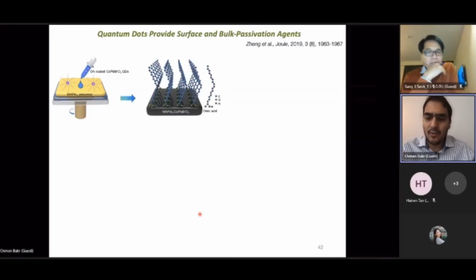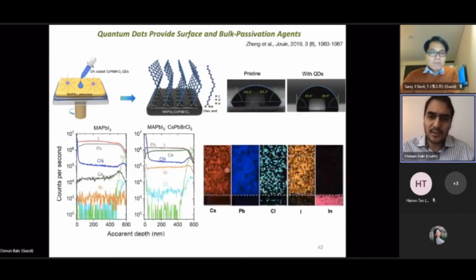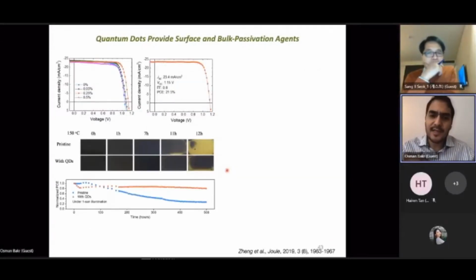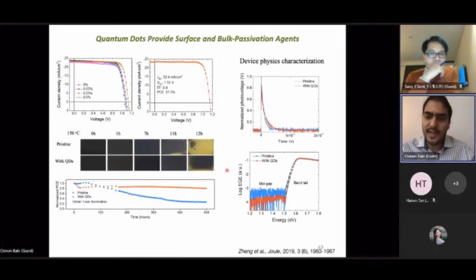In fact, one idea we had was that we could use perovskite nanocrystals in the processing of perovskite solar cells. Nanocrystals can have specific compositions, specific amounts of chlorine, specific amounts of different dopants. And because they're very dispersible and soluble in the organic solvents used to process perovskite solar cells, you could use them to dope perovskite solar cells. We showed that you could improve the stability of perovskite films and reduce the amount of defect states just by using perovskite nanocrystals as dopants and as carriers for different dopants.